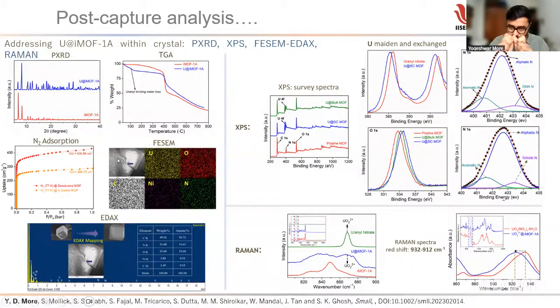Similarly, we did the crack open. What did we do? We cracked the crystal and did the FESEM within the pore of the dried crystal. And you can see the significant uranium present in this area and its percentage. And we further did the XPS survey to see how the peak shift is occurring. Compared to the metal and uranyl nitrate, in the uranium-exchanged MOF we can see the uranium binding energy shifts lower. So what does it mean? It means that the uranium is getting stabilized within the MOF structure by either a van der Waals interaction or a chemical interaction. That interaction we are going to characterize now.